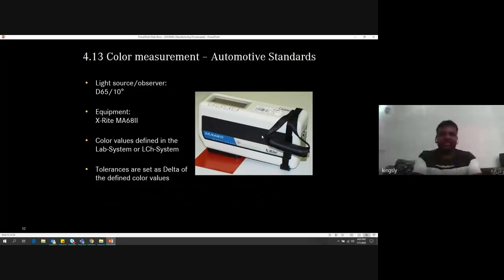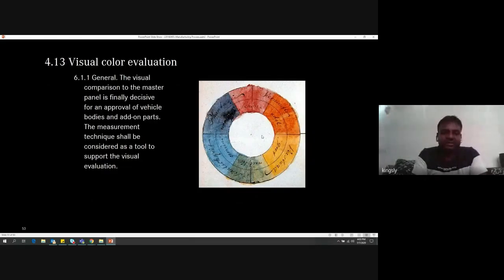This is the standard equipment that gives the color measurement, including the observer and the paint material. Then we can also define a tolerance on this measurement. When we measure the color, we can check whether it matches the standard or not. Then there is visual color evaluation. This is also done by part when we launch the new color, since it differs based on the process and the color. For example, if you have a dual color in one car, when we mix those areas, how will it look? This kind of evaluation is also done.